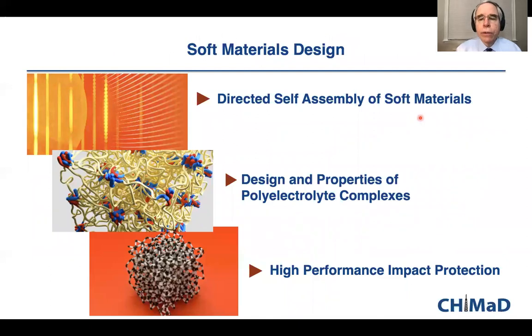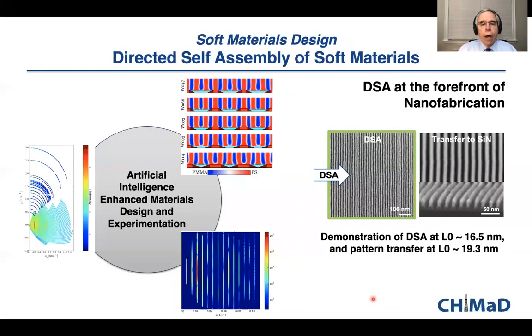In the soft materials design area, we're looking at directed self-assembly, design and properties of polyelectrolyte complexes, and high performance impact protection. The directed self-assembly is focused on making ultra-fine lines on surfaces for micro or nano electronic applications. And the challenge here is to make these lines at a very, very small pitch, on the order of 16 nanometers spacing, and do this over enormous areas necessary to build up microelectronic devices.